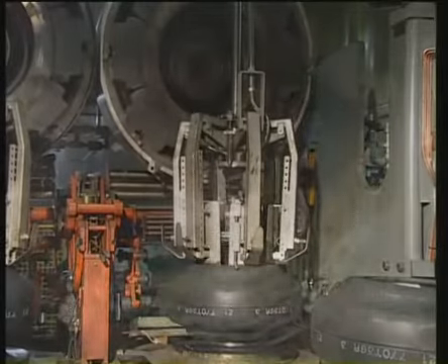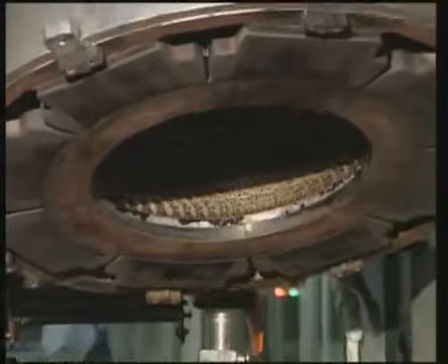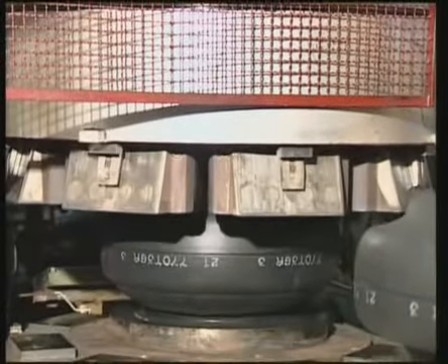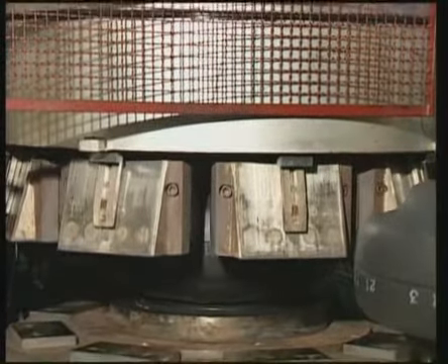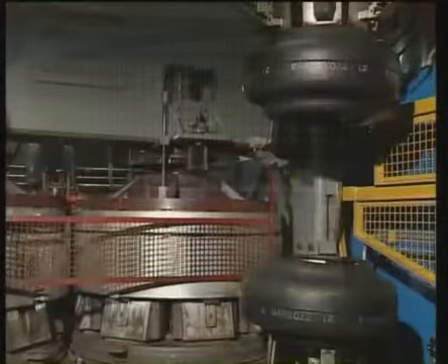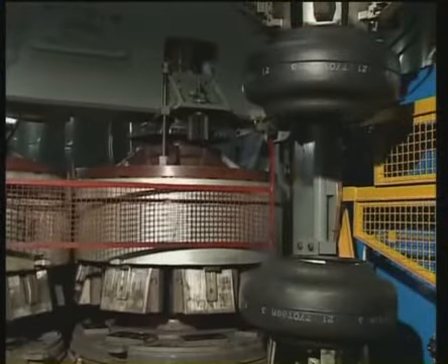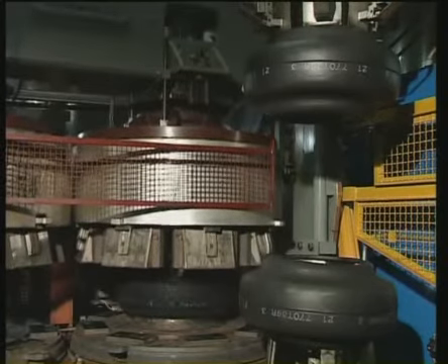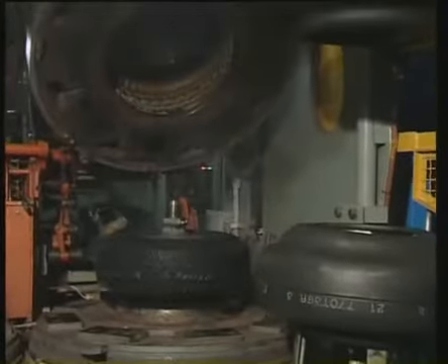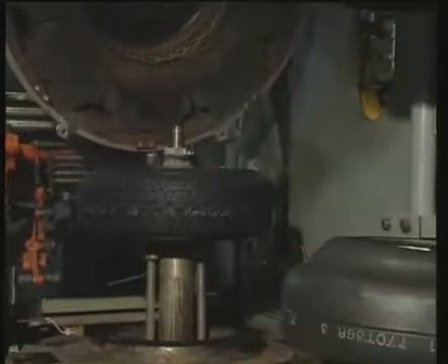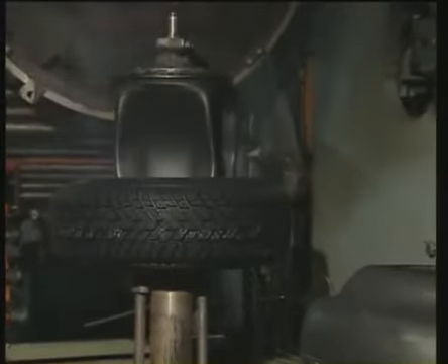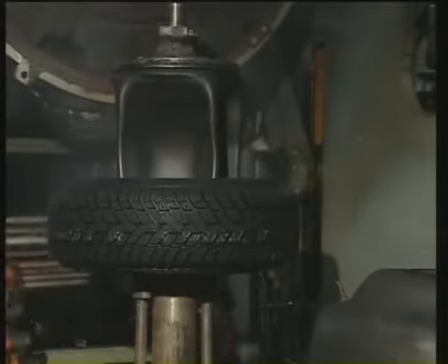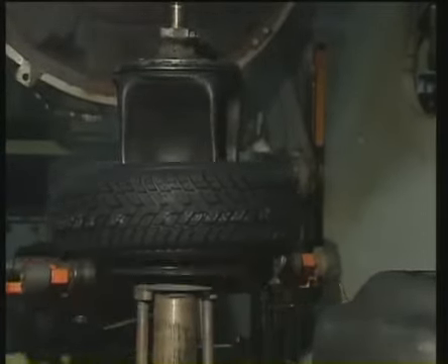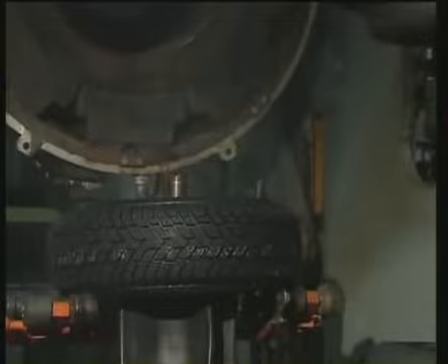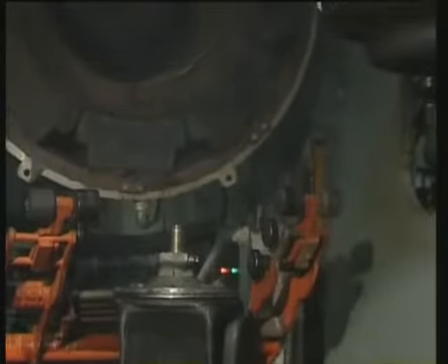High temperature steam is introduced into the mold from 180 to 200 degrees at a pressure that reaches 20 atmospheres. It takes 9 to 10 minutes to cure a car tire, and around double that time for a light transport vehicle tire. In these temperature and pressure conditions, the sulfur contained in all the compounds brings about an important transformation of the rubber, which becomes elastic and permanently loses the plasticity that, before curing, made it easily deformable.